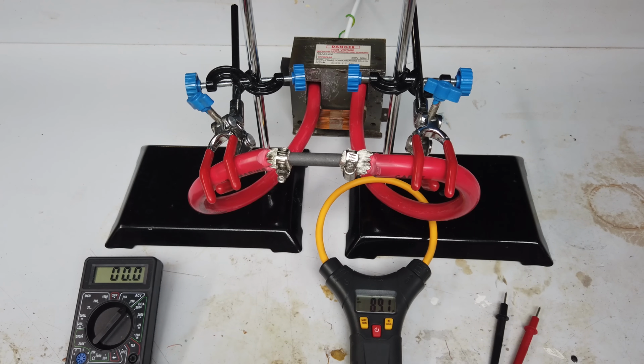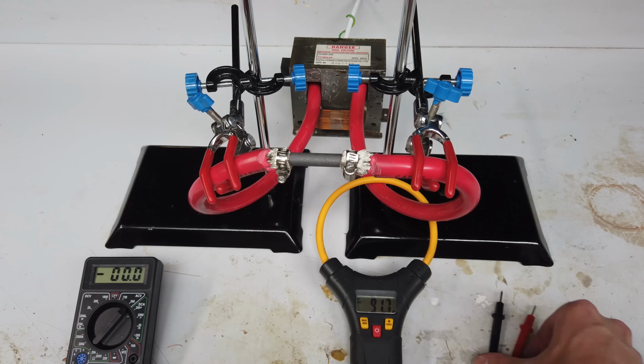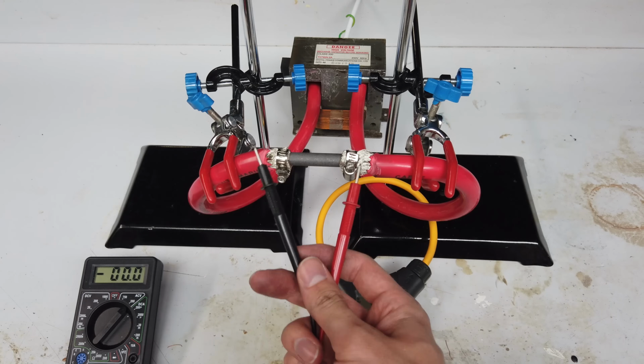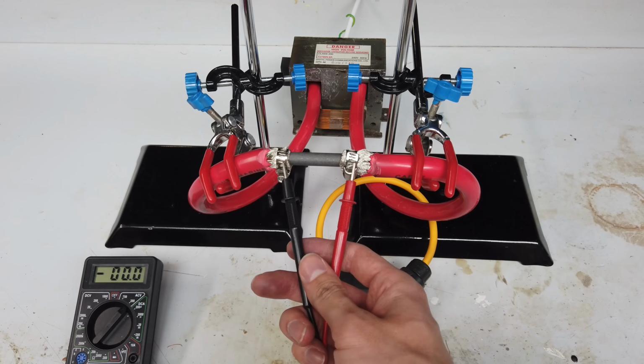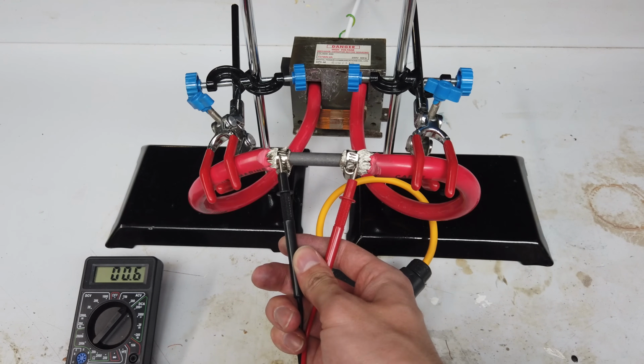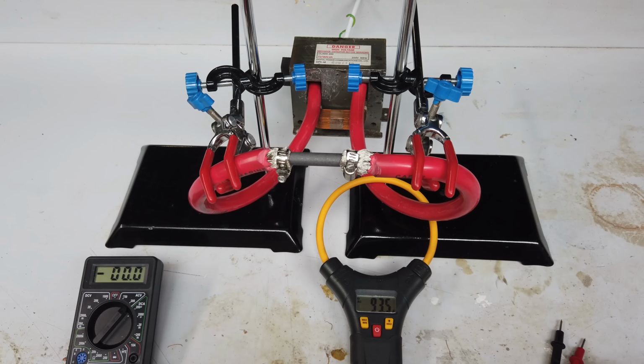All right, take 2 with a shorter graphite rod. Whew. All right, 90 amps. That's impressive for 0.6 volts, I would say. If I measure that voltage again, still 0.6. I'm very impressed that the contact resistance is low enough to allow for that much current, actually.